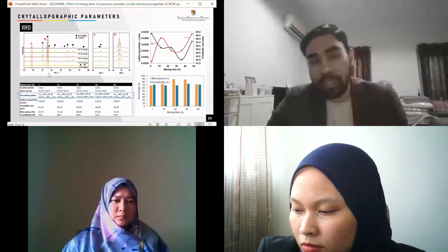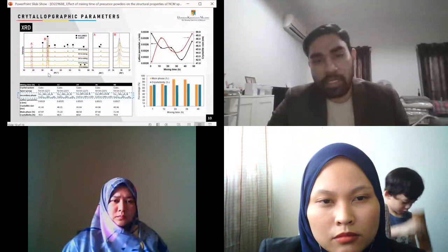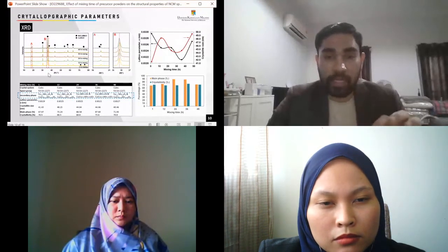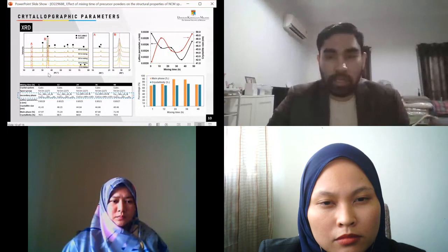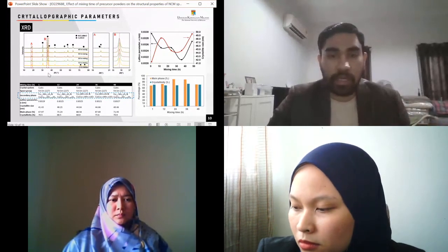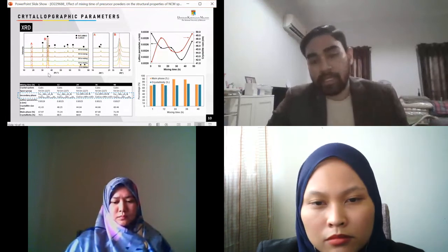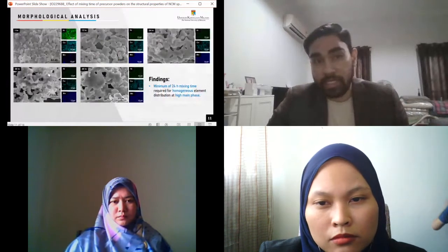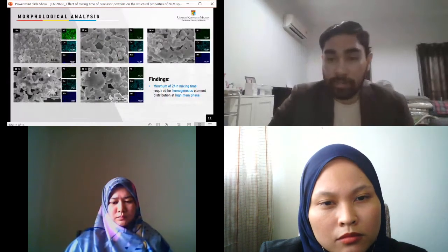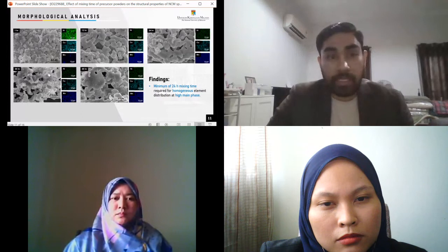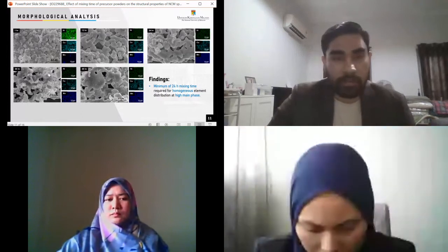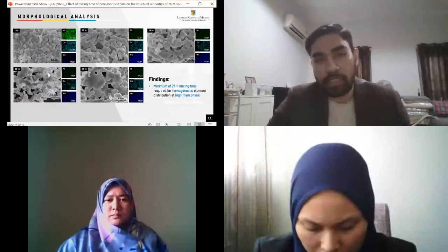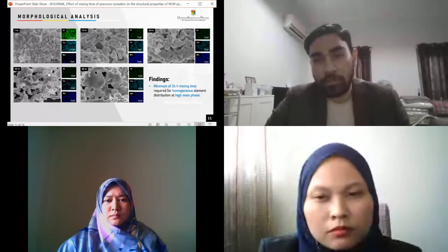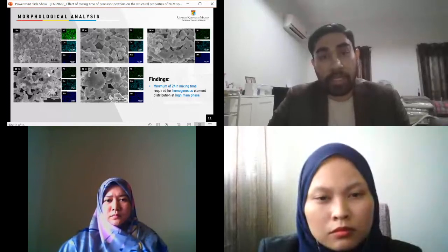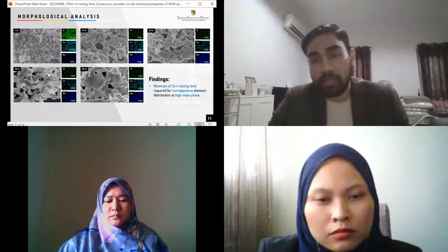This can be explained by the difference in distribution of the elements inside the spinel, where 24 hours is determined to be the most effective mixing time in producing a good distribution of the elements. And this is supported by the EDX analysis. As you can see here, at the 1 hour mixing time, the nickel especially is not distributed well enough and seems to be agglomerated on certain parts of the spinel. As the mixing time increased to 12 hours, the elements start to distribute well enough, and it increases after 24 hours.